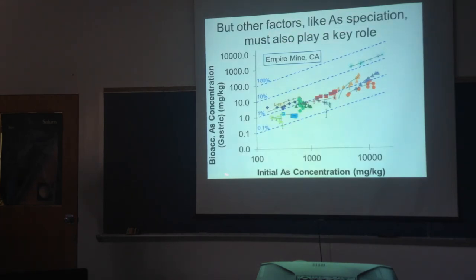Another thing he's done is plotted the arsenic concentration here on a log scale versus bioaccessible. This is the gastric leach, or the stomach leach. And we see some interesting trends within each sample. As you go to finer grain sizes, you get higher concentration of both, and they follow these trends along a relatively constant amount of bioavailability. But there is variation at a given concentration where some are more bioavailable than others,